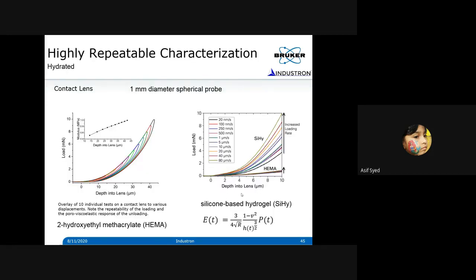And now, using the BioSoft instrument that I presented, we were able to do the indents. You can see the repeatability, how repeatable it is. These are all different indents done at different regions, but at progressively increasing load. And you can see the load displacement curves. This is a HEMA contact lens, which is acrylate based. There are two types of hydrogels we tested. One is silicone based, which I marked as SiHy, and the other is HEMA, which is acrylate based. And from the load displacement curve, we can measure the modulus.